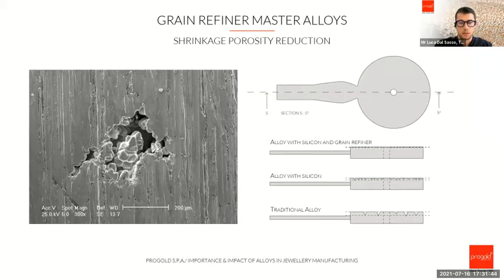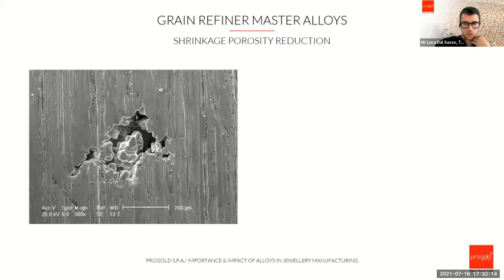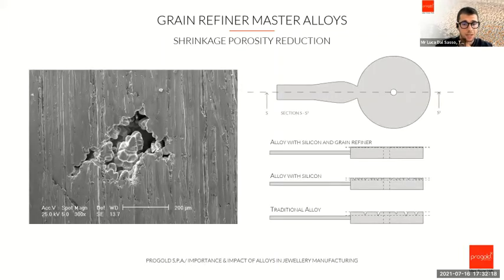In the upper side of the slide, you can see the metal we used as a sample, and the section of it. You can see the main difference between a traditional alloy, in which you have deep pores, so not many pores, but very deep. The middle one is the one with the silicon alloy, which starts helping, but doesn't really solve the problem. And the last one with the grain refiner allows us to have a very homogeneous surface. So we also have a quantity of pores, which can be even bigger, but we don't have deeper pores. So the quantity of metal we are going to remove from the upper side of the sample will be much less compared to the traditional alloy, which has fewer pores, but deeper.